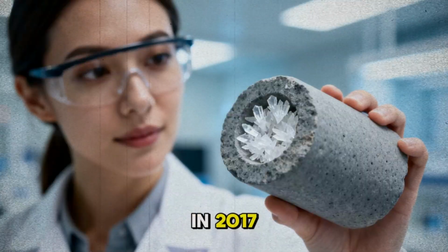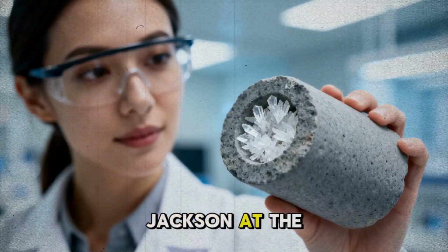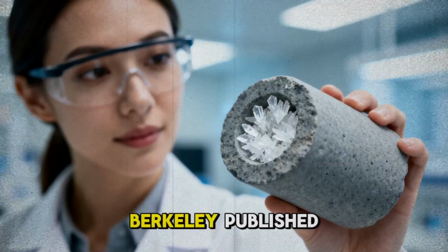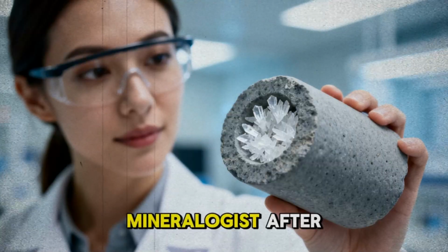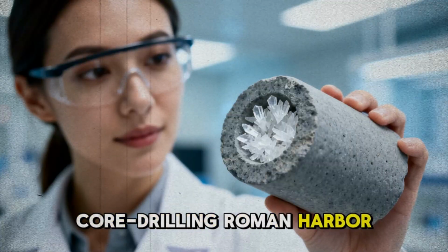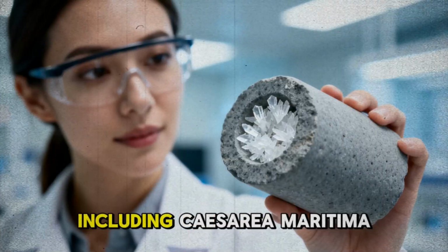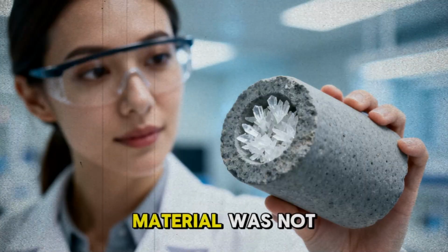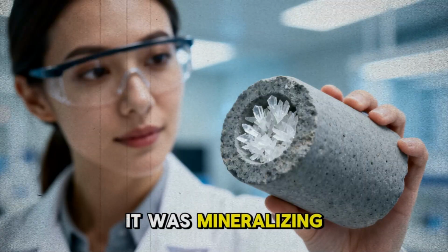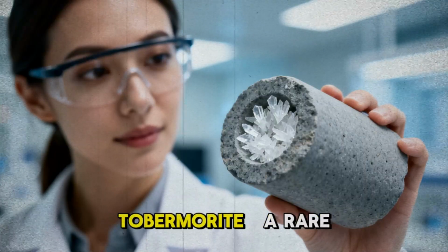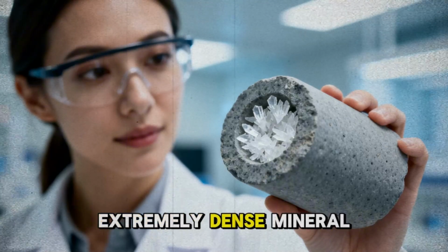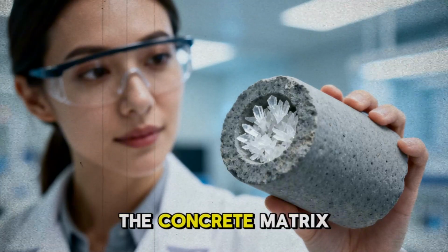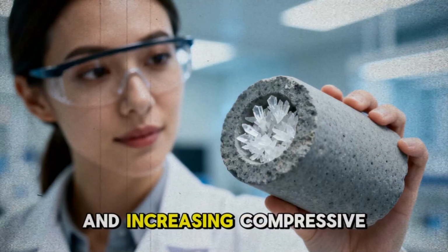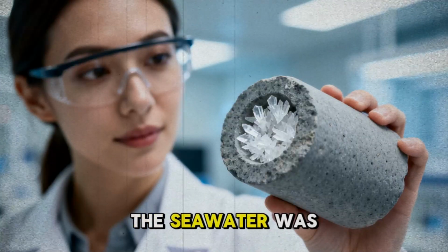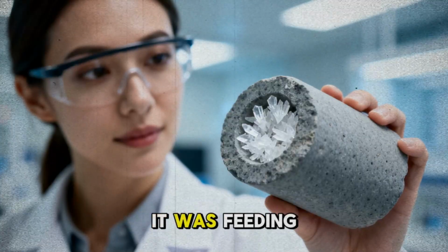In 2017, a team led by Dr. Marie Jackson at the University of California, Berkeley published findings in the journal American Mineralogist after core drilling Roman harbor concrete from sites including Caesarea Maritima and Baiae. What they found was that the material was not weakening, it was mineralizing. Crystals of aluminous tobermorite, a rare, extremely dense mineral, were growing inside the concrete matrix, filling microcracks and increasing compressive strength over time. The seawater was not degrading the concrete, it was feeding it.